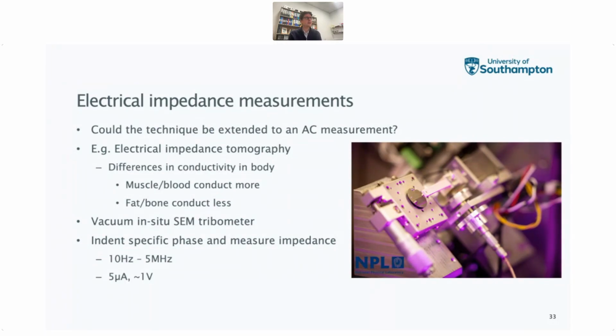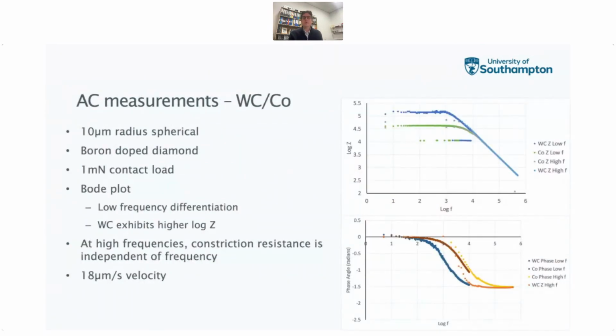And so we attempted this again using the vacuum technique at the National Physical Laboratory, again for oxidation mitigation. And this time we're going to sweep through a number of different frequencies from 10 hertz all the way up to 5 megahertz. And we're going to apply a 5 microamp current. We let it float a little bit higher, about 10 volts, but because it's such a small current, it went to about 1 volt really to take the measurement. And then what we can do is we'll use a 10 micron radius spherical boron doped diamond with a 1 millinewton contact load. And we can start putting this into the two phases.